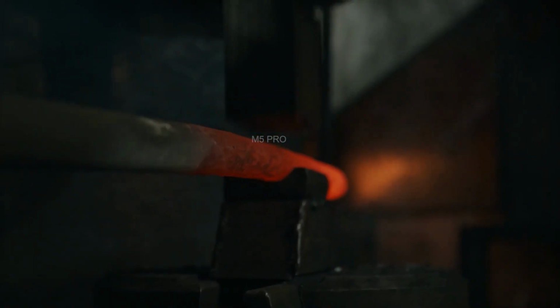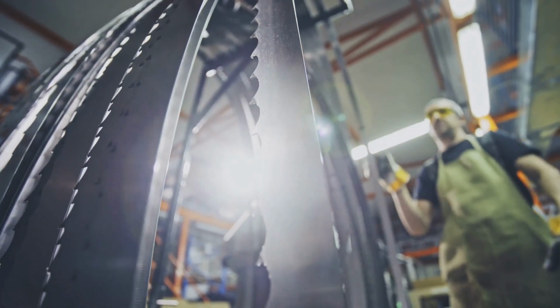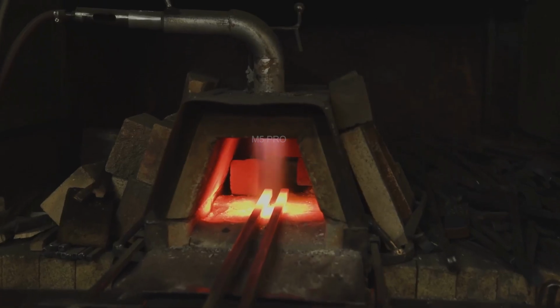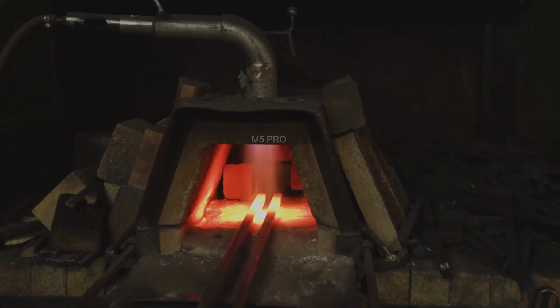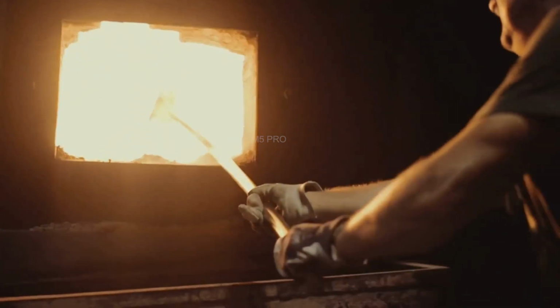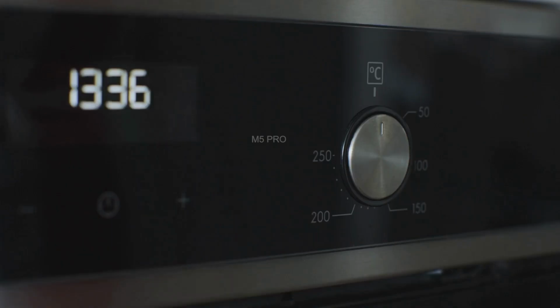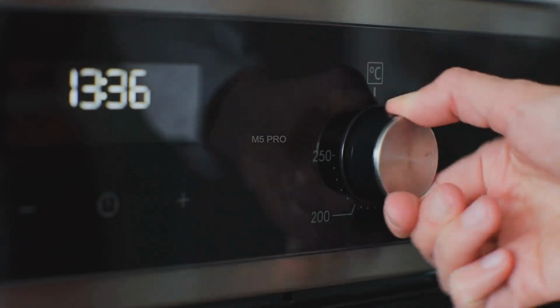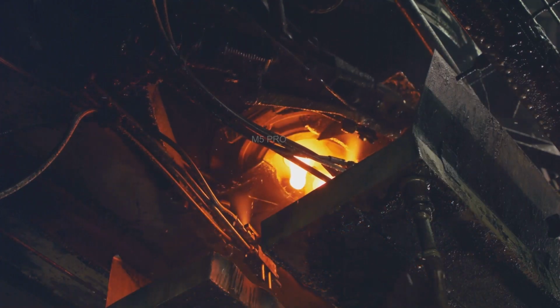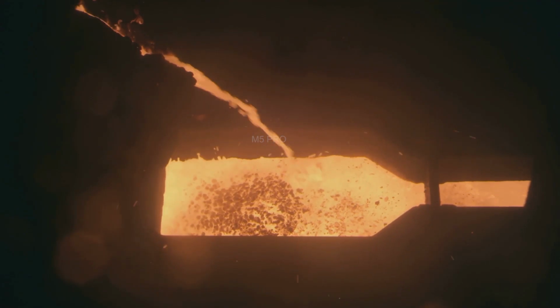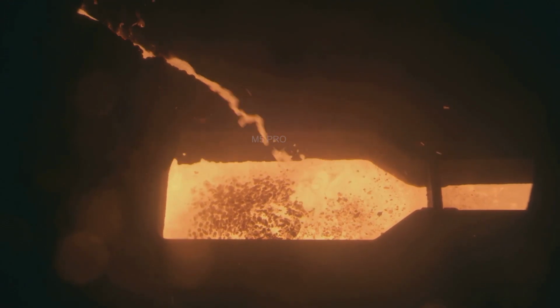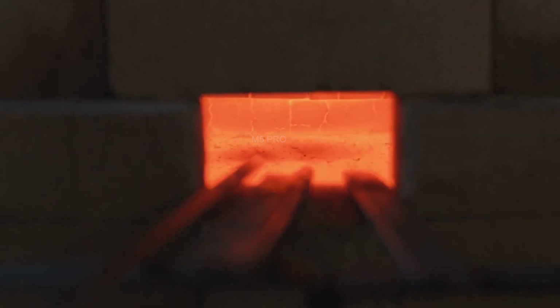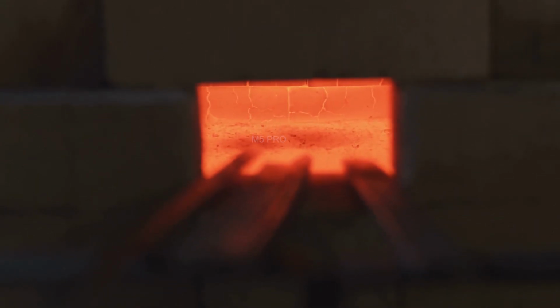The first step is called hardening, or austenitizing. The shaped blades are carefully loaded onto racks and placed back into another precisely controlled furnace. They are slowly heated to a specific critical temperature, usually around 1,500 degrees Fahrenheit. This temperature is vital. It causes the carbon within the steel to dissolve evenly into the iron, forming a new internal structure called austenite. Holding it at this temperature ensures the entire blade is uniformly transformed.